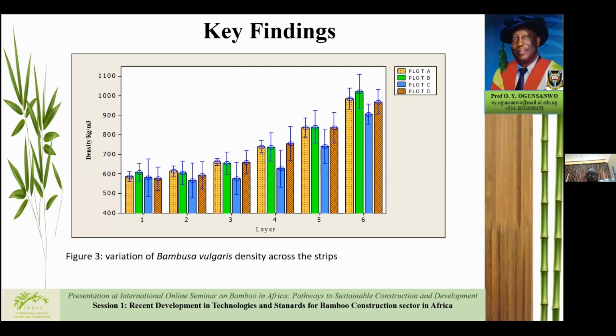Key findings in this research is that we have density variations according to the layers. Layer 6, being close to the outer coating, had the highest densities for all the 4 sites, and then layer 1 the lowest for all the inner sites. It is important to note that in density distribution, plot B, which is located in one of the southern moist forests, particularly in Olodo, Ibadan, Oyo State, Nigeria, had the highest bamboo density, while the one taken from Jericho in Ibadan had the lowest bamboo density, as seen in figure 3.